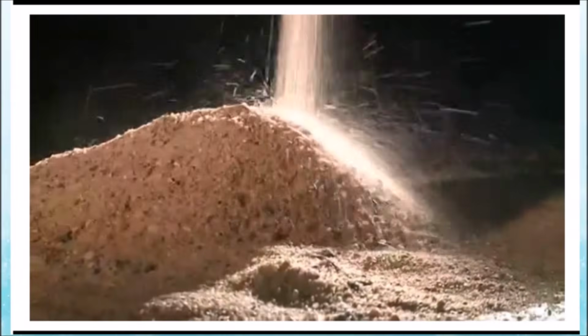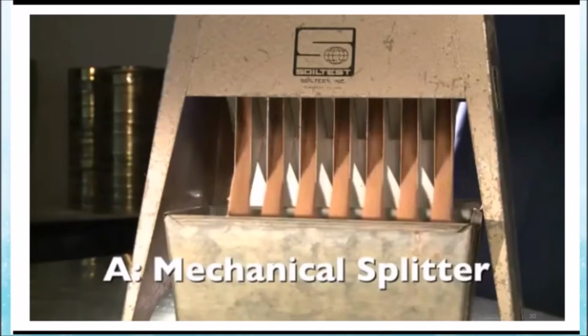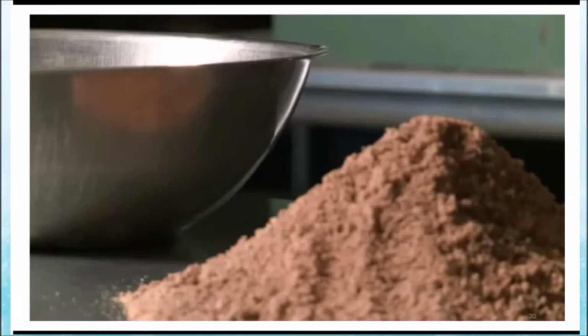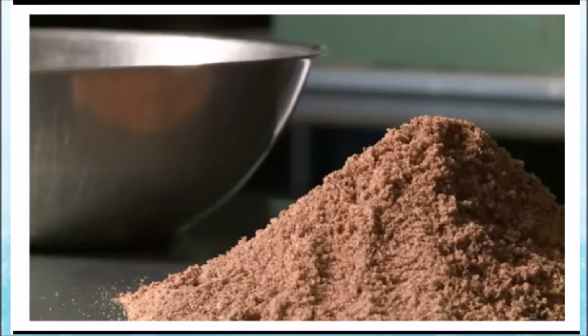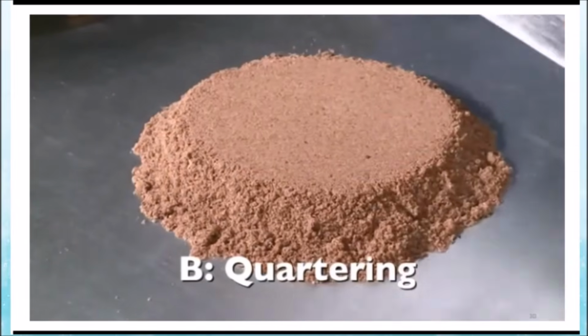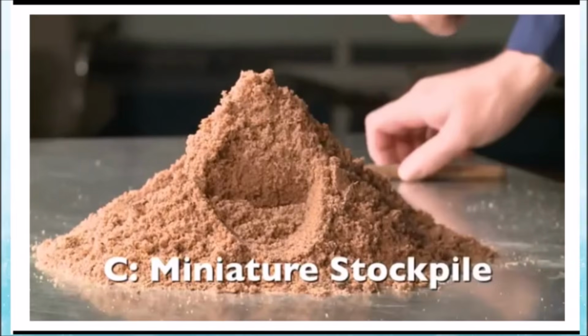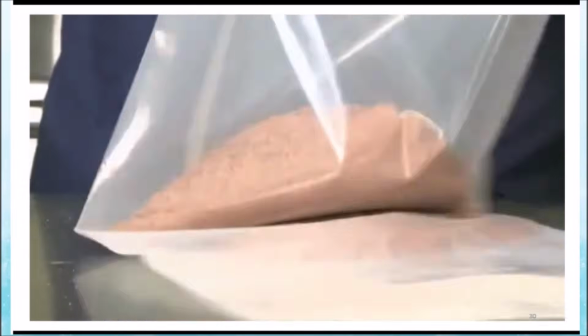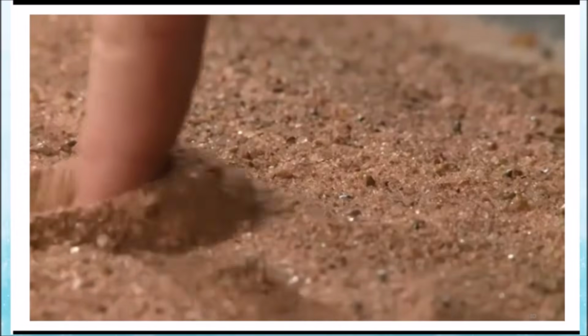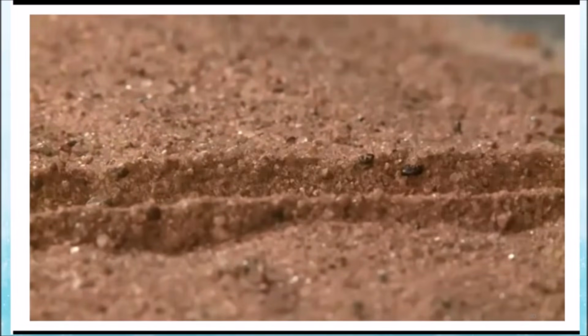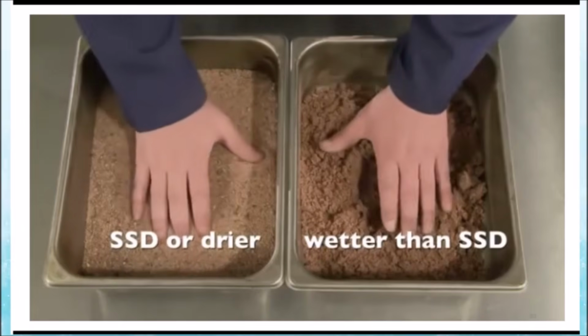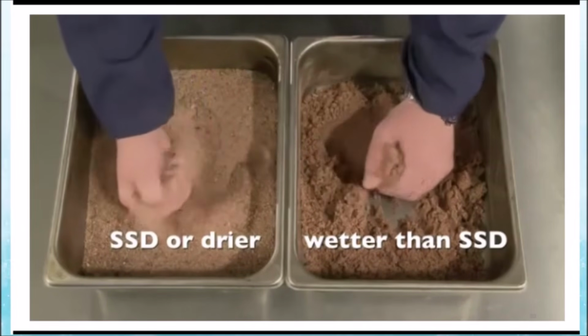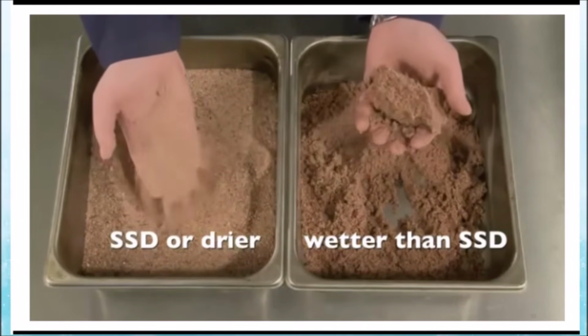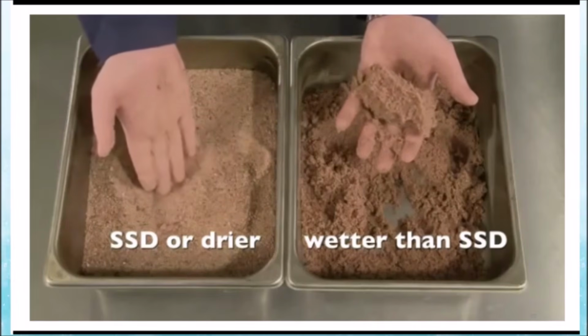For samples that are saturated surface dry or drier, use method A, the mechanical splitter. If your sample is wetter than saturated surface dry, use method B, quartering, or method C, miniature stockpile. If the moisture condition of your sample is not apparent, determine its condition by performing the field hand test. Just squeeze a handful of material. If it retains its shape, assume that it is wetter than saturated surface dry.